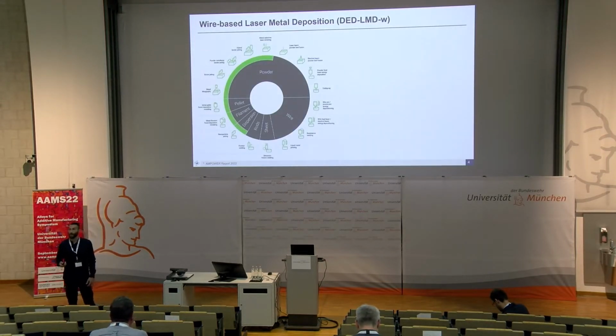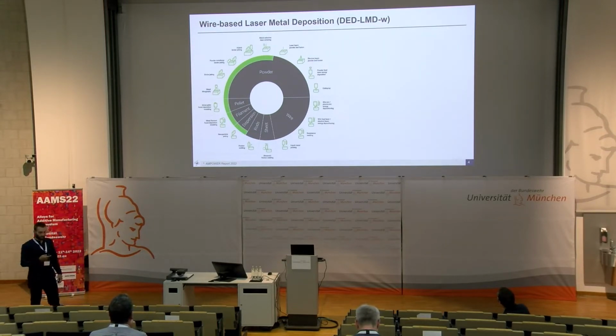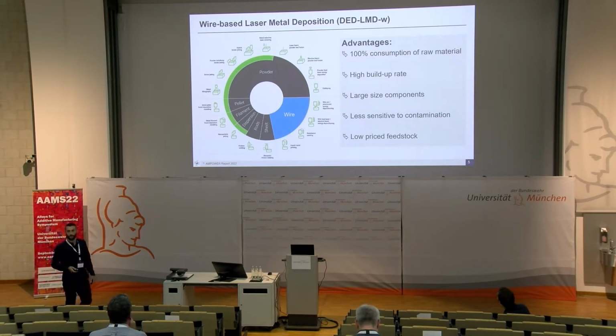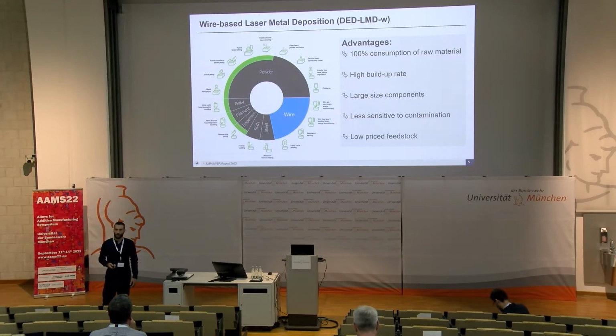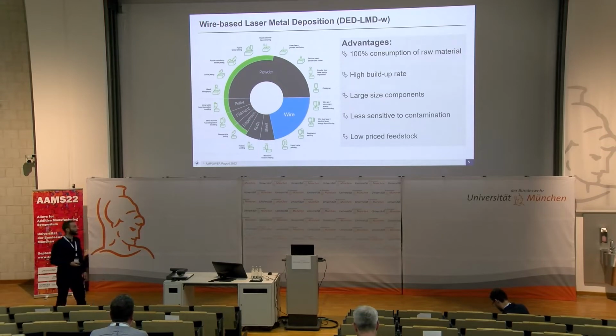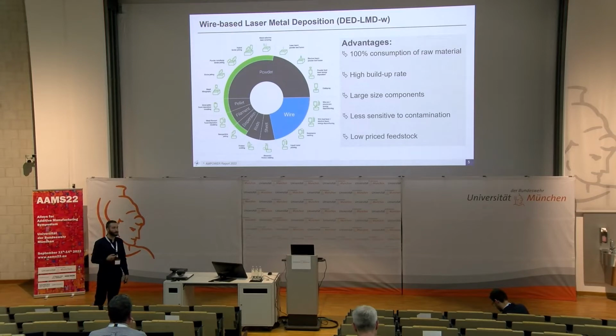So first, we heard a lot about powder-based processes, and I think that's completely normal. We have like 40% of the sales in the complete additive manufacturing market going to powder-based processes. But today I want to speak about a wire-based process. And in wire-based processes, we have a few advantages over the powder-based process. We have nearly 100% consumption of the raw material. We also have high build-up rates, so that we can build large-scale parts in pretty short times. And when we look at the surface of the feedstock material, we have a lot less surface, so we are a lot less prone to contamination through oxide or other elements. And also the feedstock material, if we use standard wire, is pretty low priced.